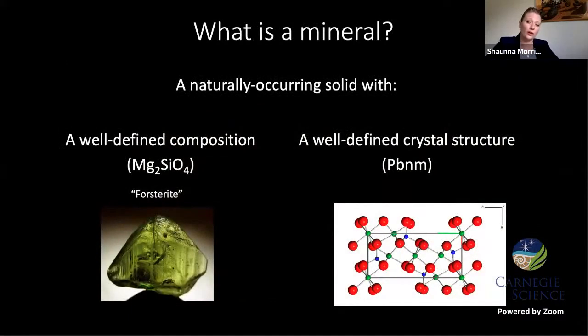We can even go a little farther than saying simply which mineral is present. We can actually estimate the chemical elements or atoms that are present in the mineral beyond their idealized chemical formula. For instance, looking at olivine, which is very abundant on our planet, making up most of our upper mantle, but it's not very stable at the surface, so that's why you don't see it a lot. The olivine we're seeing here is the magnesium version, which is called forsterite. It has an ideal composition of two magnesium atoms, one silicon atom, and four oxygen atoms.